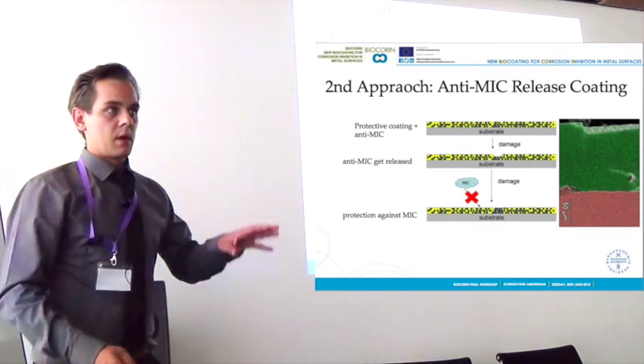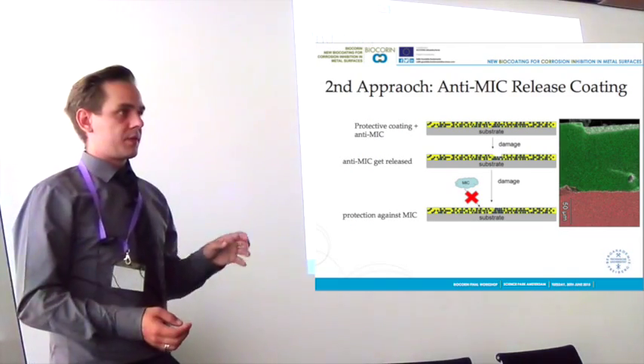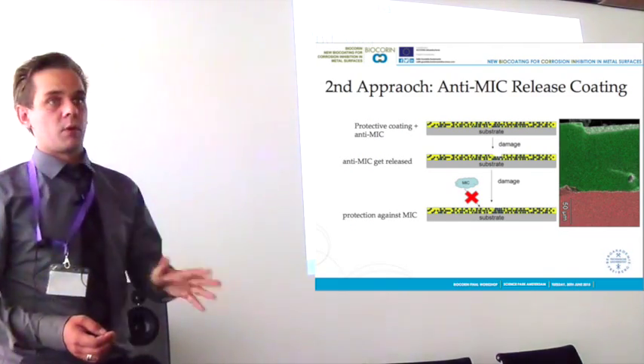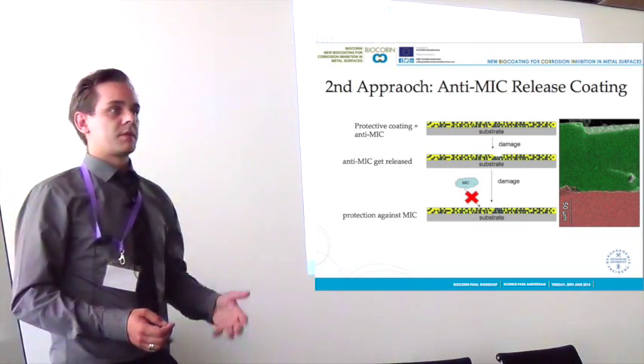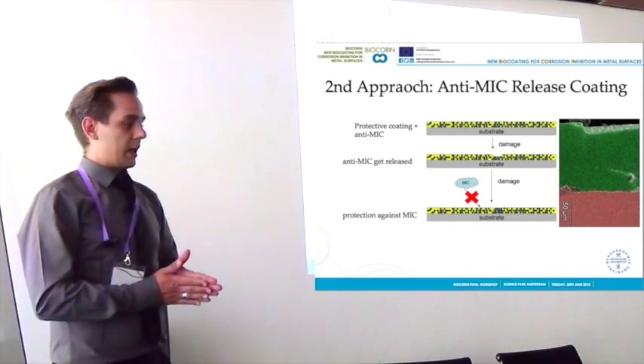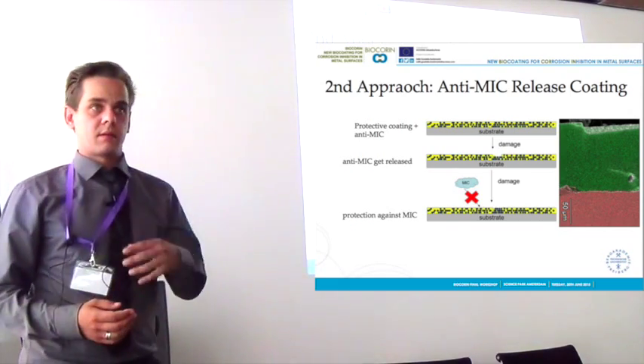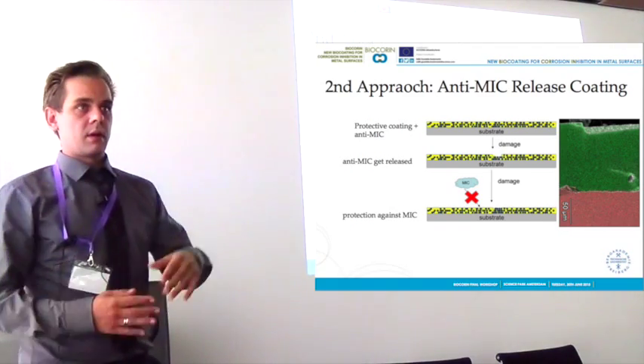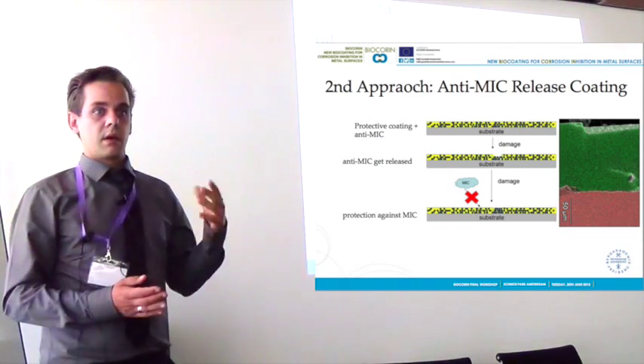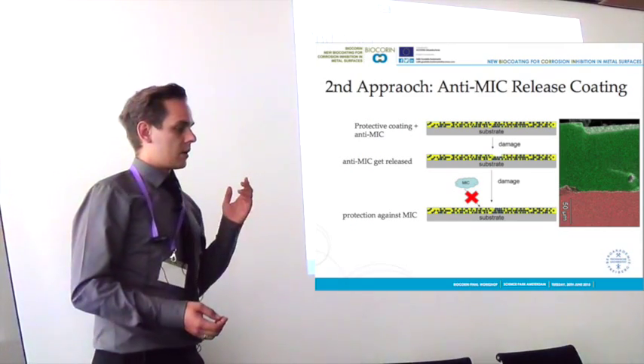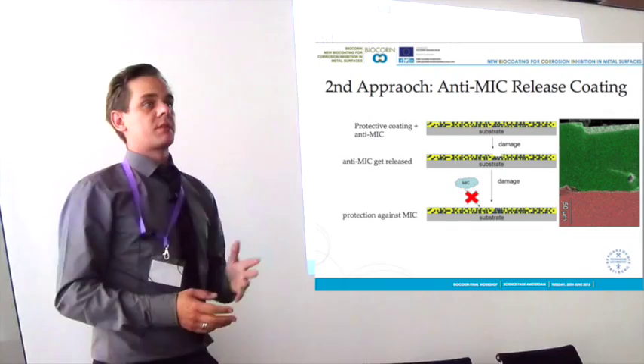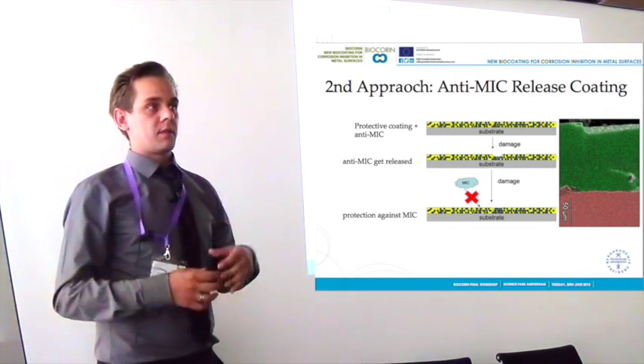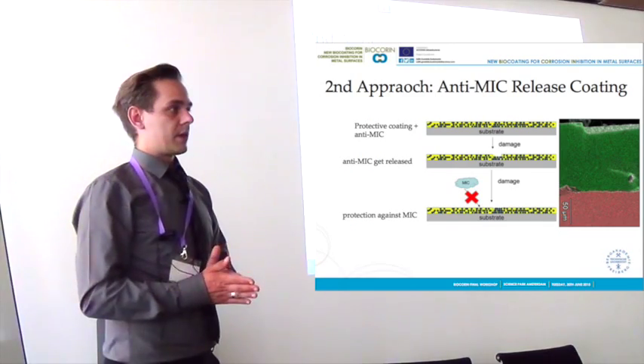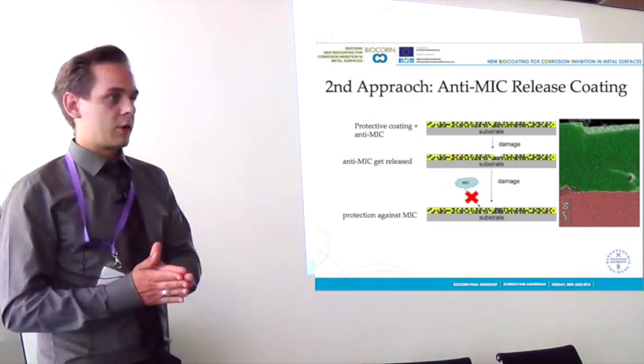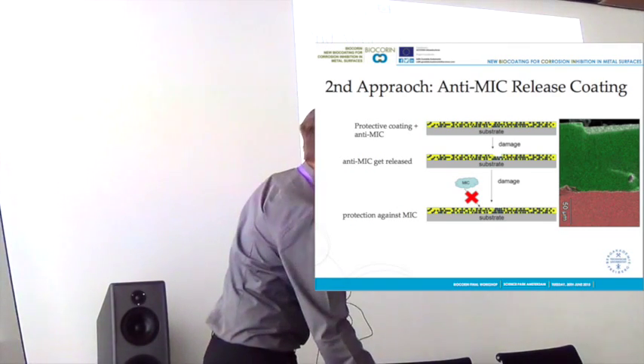This was designed as an anti-mic release coating. The basic idea was here to use the protective coating that was working very well, and to integrate the microorganisms into the coating. And as long as the protective coating stays intact, that means there is no scratch, there is no hole, the microorganisms should be in the coating. And once a damage occurs on the surface, the microorganisms can get released and colonize the surface and should prevent microbial corrosion.